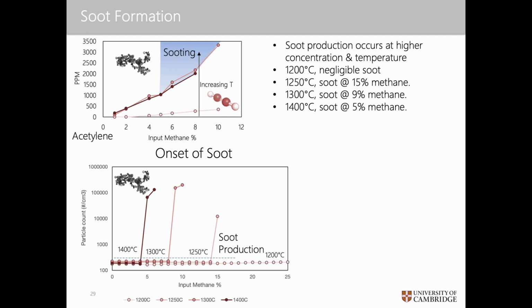And what one sees is that as you input more methane, you get an increasing amount of acetylene up to a point. And eventually, as you start increasing methane and increasing temperature, you ultimately max out on the amount of acetylene in the reactor, because the acetylene starts to get consumed and produced into soot. So everything up in this region starts to be soot production. And so we can measure that in another way, of course: we can put in different amounts of methane, and we can start to increase the temperature and see when soot production starts to come.